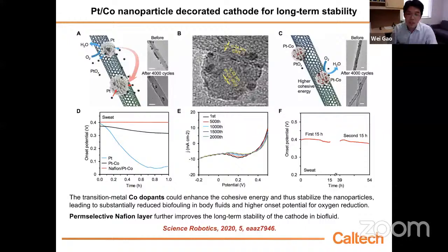So in this case, we get much better performance in body fluid. You see in sweat, if you only use platinum, the onset potential decreases quickly within 1 hour. If you use platinum cobalt, the decrease is very slow. And if on top of platinum cobalt we coat a Nafion film for anti-fouling, we can get a stable performance over a very long period of time, like here, 15 hour operation.